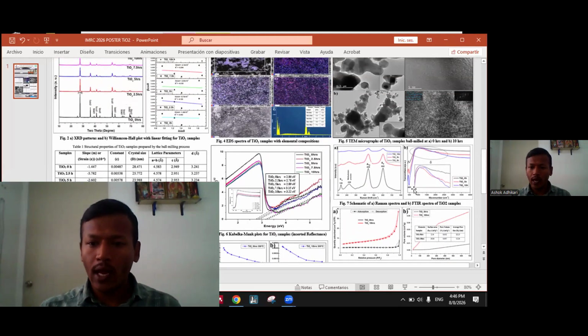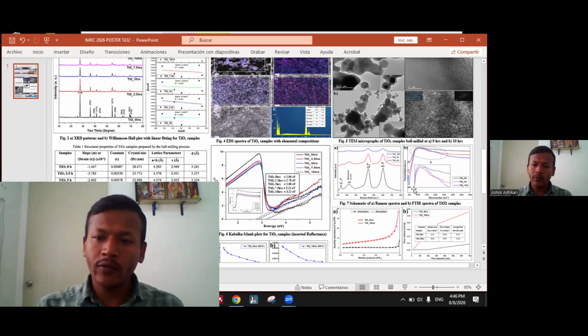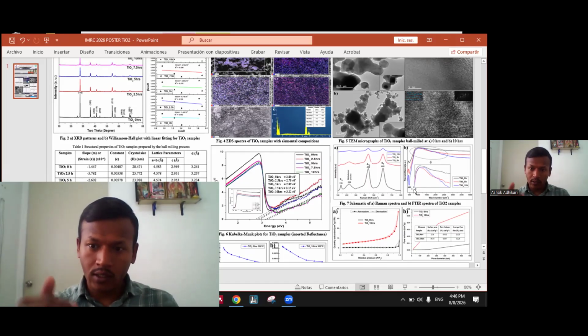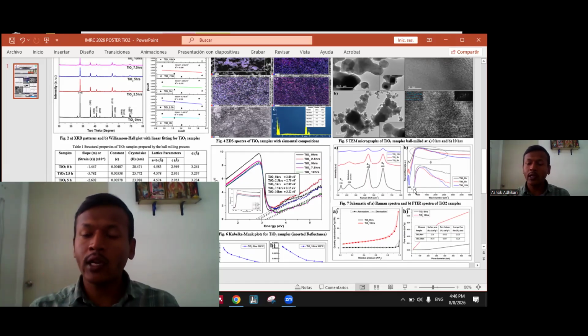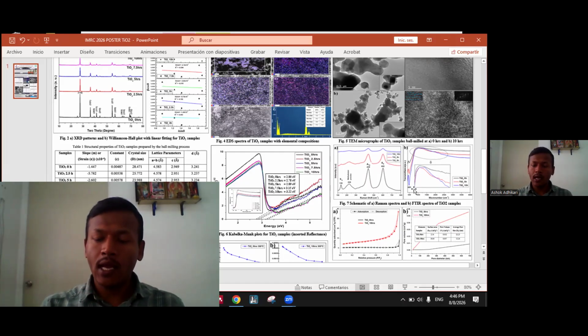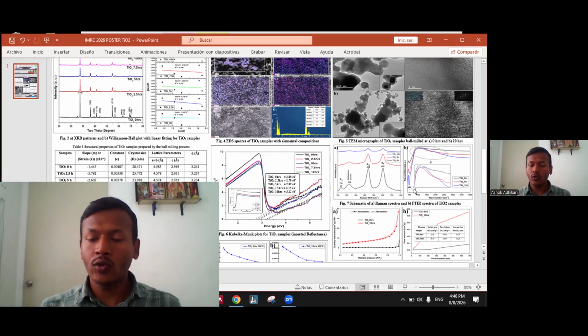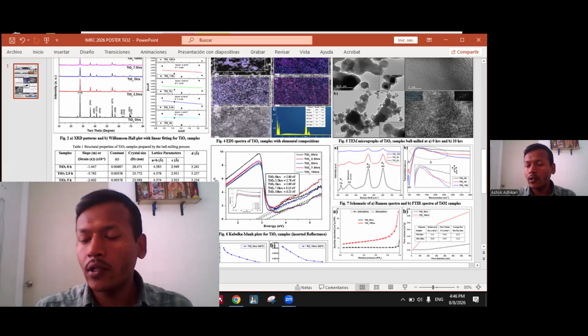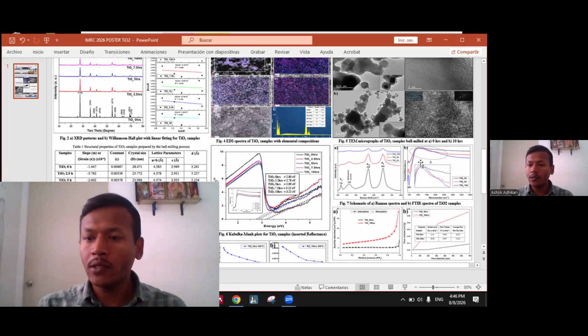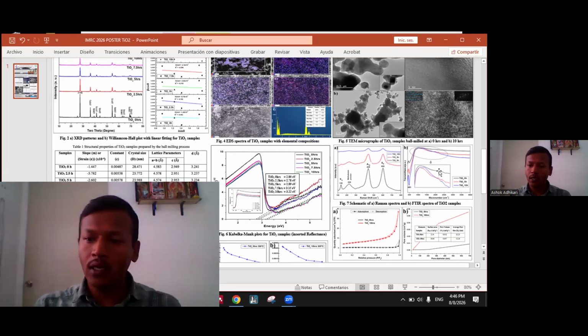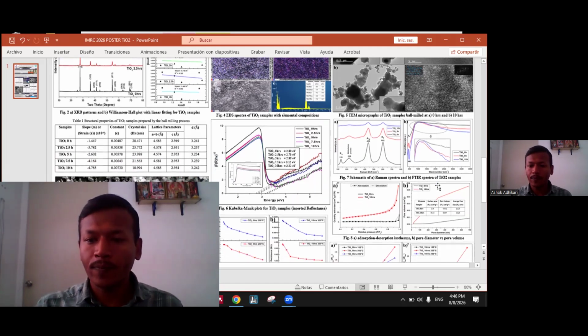And from the Raman, we have seen four different peaks. We have B1g, A1g, and a multi-phonon process, Eg. These peaks also show that with increasing milling time, for 0 hours, 5 hours, 10 hours, the intensity decreases and the full width increases. So this shows the presence of defects, or we can say low efficiency of the samples. And similarly, from the FTIR results, the high intensity of the peaks shows more defects for the samples obtained from higher milling times.